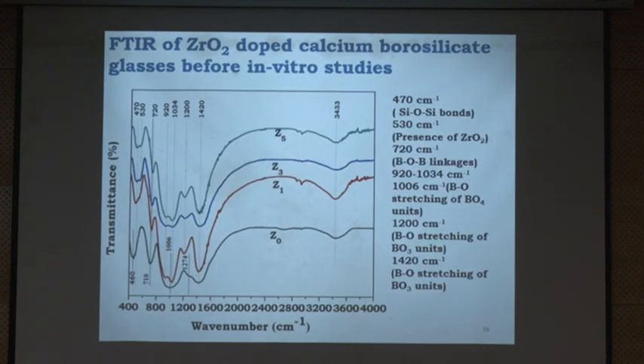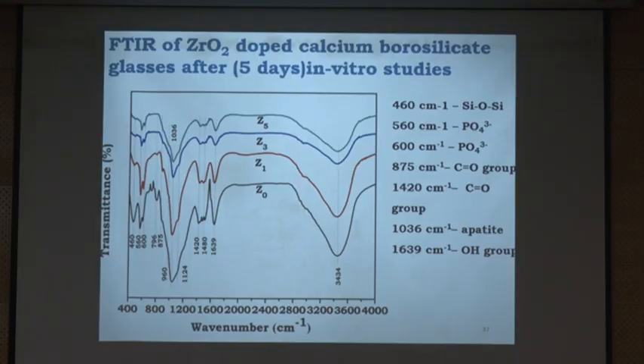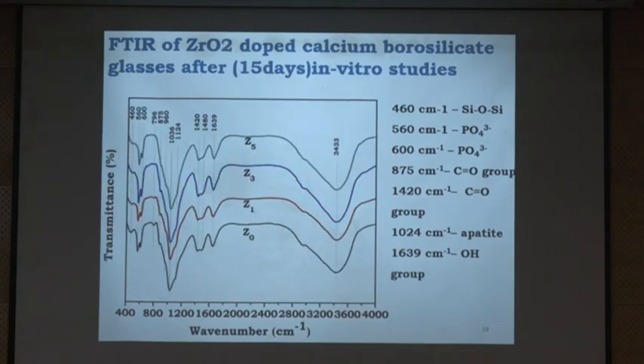Similarly, with the FTIR, this is before immersion. We recorded the FTIR, and we saw some functional groups which confirm the presence of the metal you have used. But after immersion in simulated body fluid, recorded after 5 days, we can see peaks at 560 and 600, which are related to the hydroxyapatite. So we can confirm from FTIR also that the layer has deposited on the surface of the material.